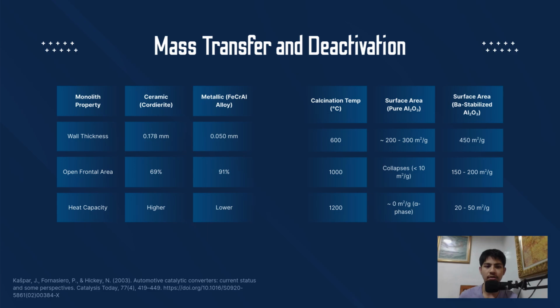Lastly, we consider the physical limits of these monolithic systems. Mass transfer is governed by geometry. Metallic monoliths have thinner walls than ceramic ones, allowing for a 91% open area and faster heating. However, these systems are prone to severe deactivation.